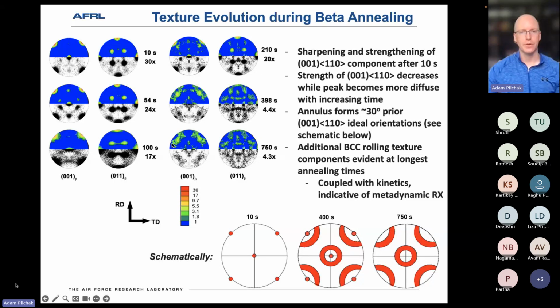And it's also interesting that those are, I think, roughly in the range of 20 to 30 degrees away from the initial sharp orientation there. And so if you now look through the 100 pole figures, I think you start seeing that effect, especially once you get to around 400 seconds, where we've got these rings starting to form, and then we've completely lost our original texture at 750 seconds, which corresponds to complete recrystallization.